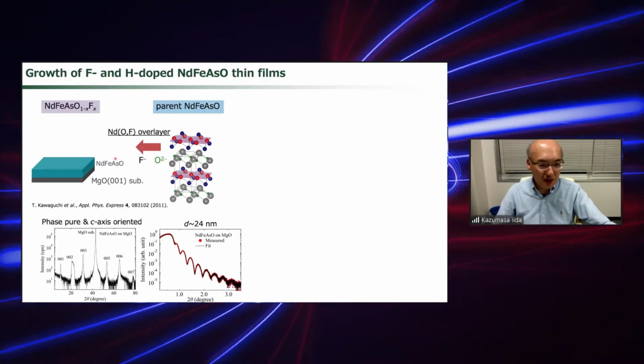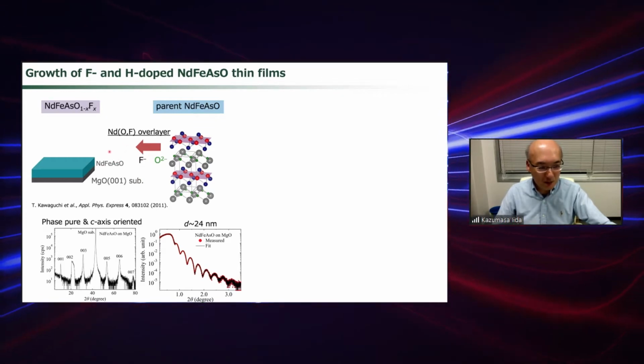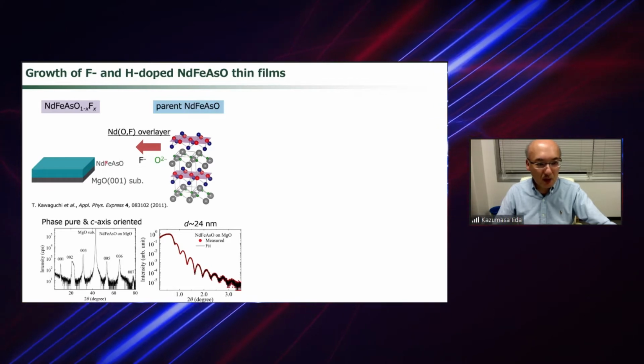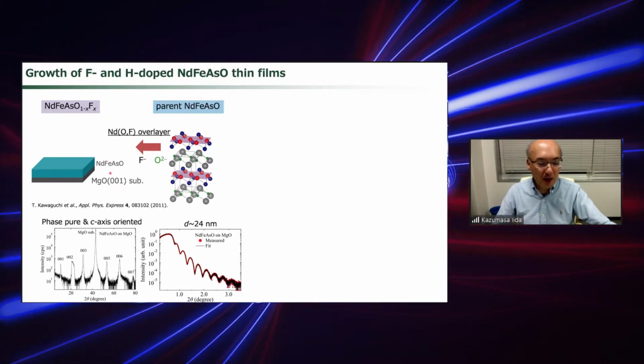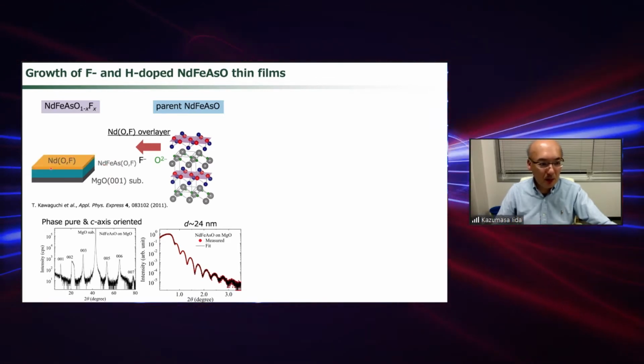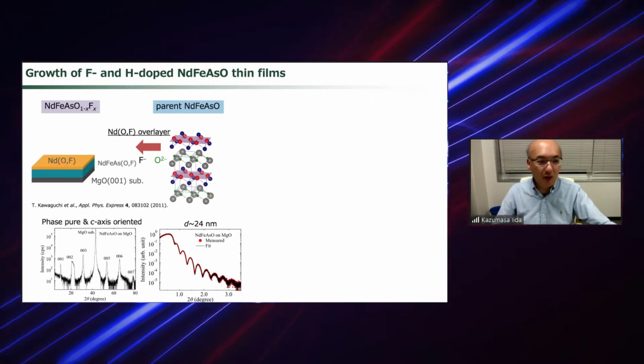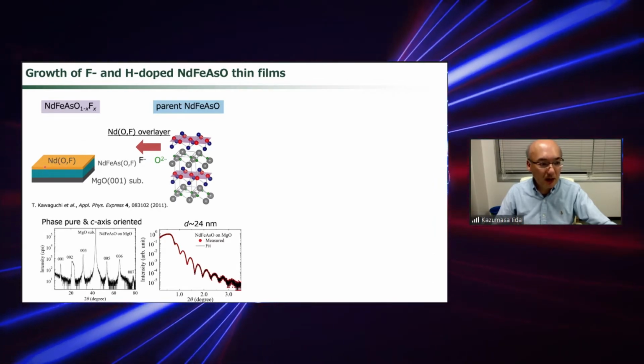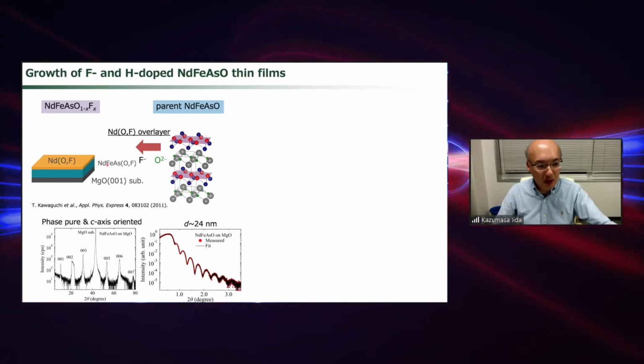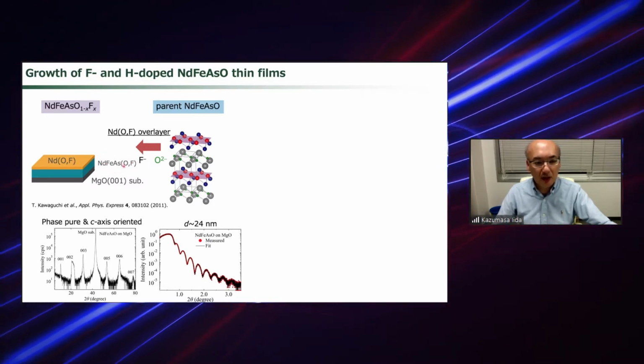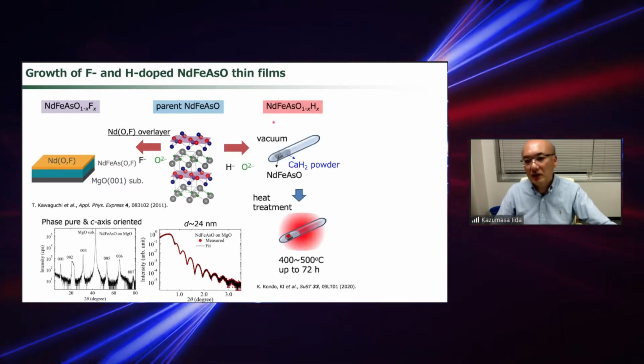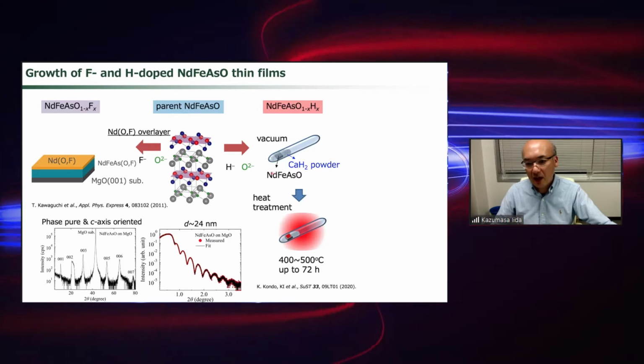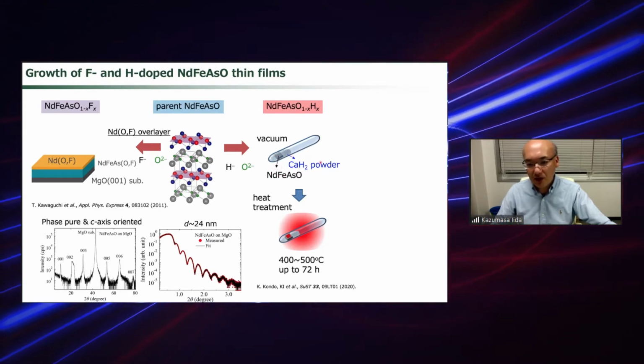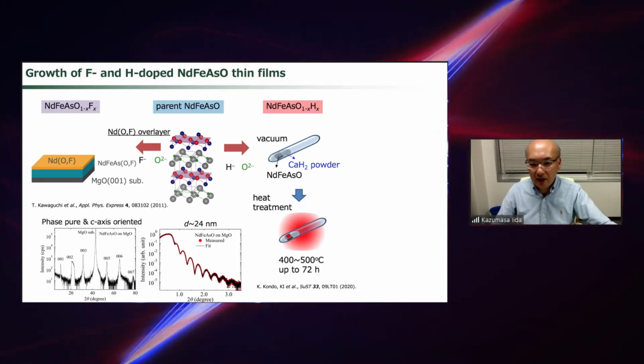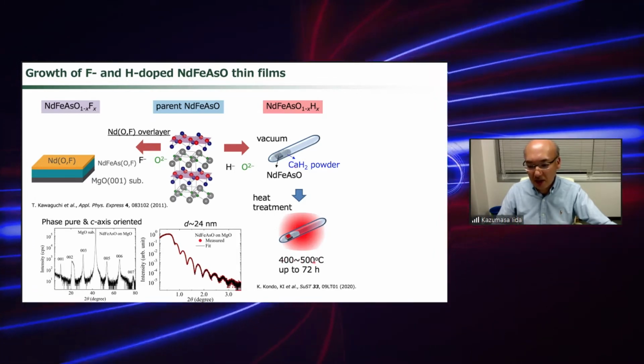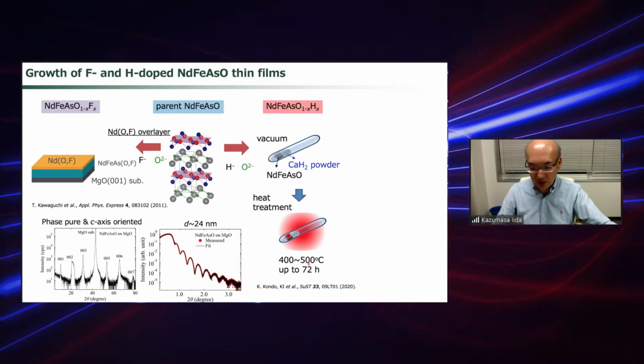But unfortunately, this fluorine doping also has some problems. So that is the reason we employed the so-called two-step process. First, we prepare the parent compound, and then we deposit a neodymium oxyfluoride overlayer. During the deposition, the fluorine diffuses into the parent compound and becomes fluorine-doped superconducting 1111 films. For the hydrogen-doped 1111 films, we sealed the parent compound together with calcium hydride powder and annealed at 400 to 500 degrees for up to 72 hours.